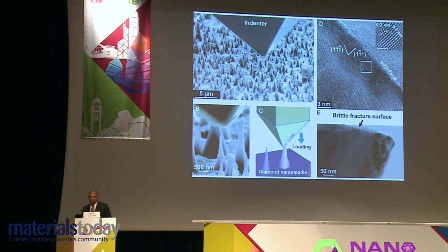So here is the microstructure that was produced. In your top left, you see the indenter coming down, and there is a large number of nano needles sticking out of a substrate. On the right-hand side, you have a high-resolution TEM image of the surface of diamond. In figure B, you see the diamond tip, like an AFM tip or a nano indenter tip, coming down to push one of the diamond needles. Figure C shows a schematic of how that happens. And then, of course, if you push it far enough, diamond will catastrophically break and you'll get a brittle fracture surface. You can take the orientation of the fracture surface with respect to the crystallography of a single crystal, and you can demonstrate that this is a classic brittle fracture process that takes place.